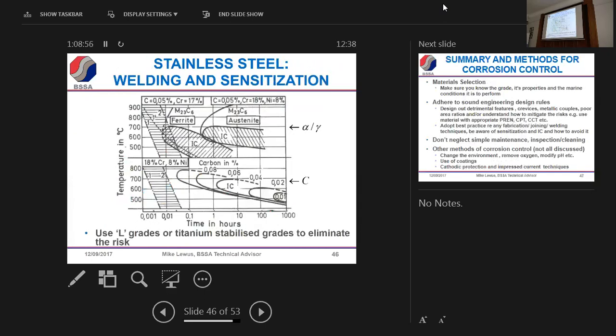And this just shows you temperature versus time to the formation of chromium carbide. In the metallurgy world, you often get these C-type curves. Each one of these C curves shows you the point at which you can expect chromium carbide to form. This set of curves is 0.08% carbon in an 18/8, like a 304 material. This is a log scale, in hours, so we've got 10 minutes there. We've literally got a few minutes before we get chromium carbide precipitation at the high carbon end.